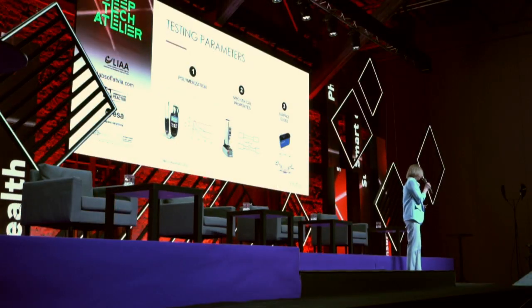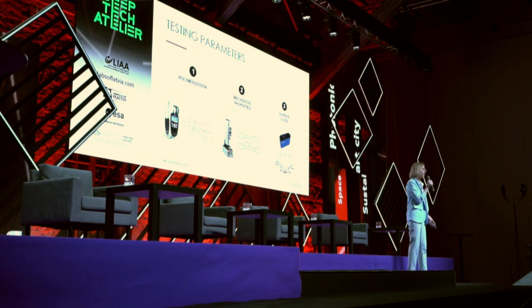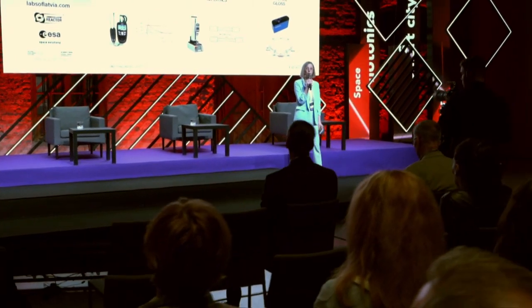One of my colleagues went to Germany to a manufactory where they make different testing equipment. And for a 3-day period, they tested all possible abrasion resistance equipment. This was the team who previously developed the coating abrasion equipment for BMW. And we really had hope that they could get some solution for us. But unfortunately, no, because our coatings are really thin. But we worked hard and we developed this equipment by ourselves. And now we can test the surface gloss and abrasion resistance in 1 day instead of 3 weeks.